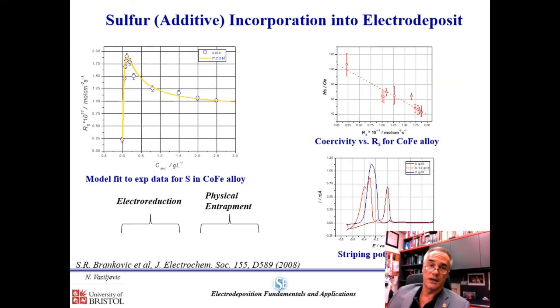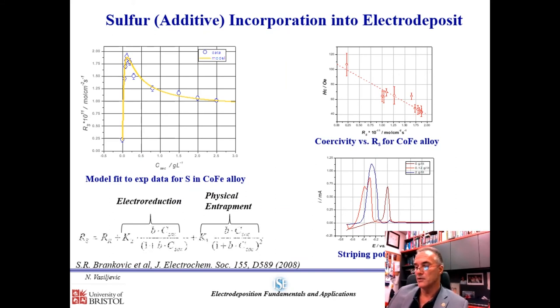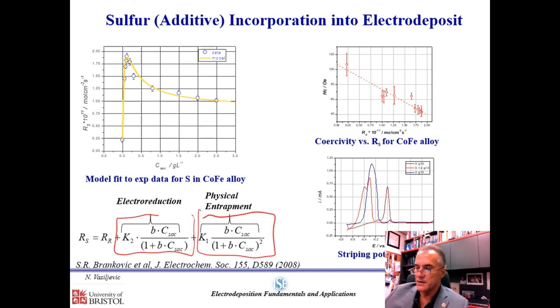Here I also show you another phenomenon that is related to the presence of the additives in the plating solution, which is that additives do incorporate into the deposit. They either incorporate through an electroreduction process, where basically the molecule of additive is broken down into fragments and eventually forms some kind of an intermetallic compound with the deposit, or it's physically trapped and buried in the deposit during the growth. Both of these processes are described by these terms here, and they are also a function of the concentration of additives in the solution, and those electroreduction and physical entrapment constants.